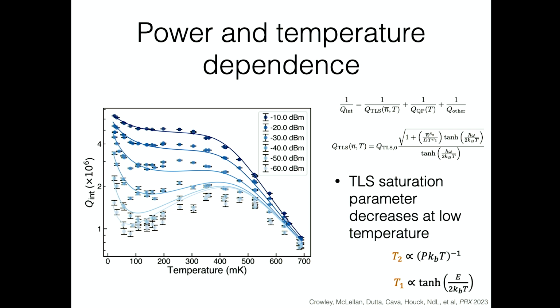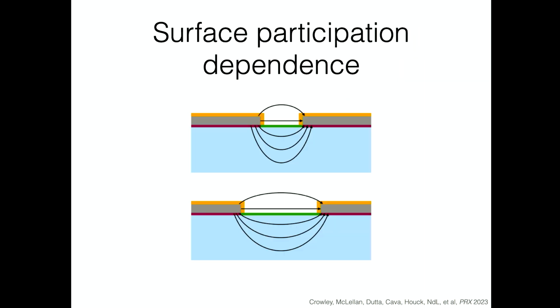So what this allows us to do is, let's say I've really screwed up my packaging, and now I have some radiative loss. Then what I know is that that is not going to have any power or temperature dependence, so that will show up as all these curves being a little bit squished. But I can still independently fit all the curvature and get out this two-level system component. Okay, so the key playbook here is you come up with a measurement strategy that gives you access to a material parameter. And then we can take that material parameter and do things like make different geometry devices. So as we make these things bigger, we can change the surface participation.